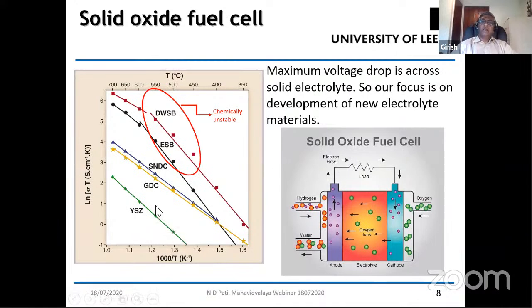Presently, the solid oxide fuel cell uses an oxide ion conductor, which is yttria stabilized zirconia, and also gadolinium oxide doped ceria as the solid electrolyte. There has been some research done into bismuth oxide based electrolyte, which has much higher conductivity than yttria stabilized zirconia or gadolinium oxide doped ceria. However, bismuth oxide based electrolytes are quite unstable at the low oxygen potentials that are present at the anode of a solid oxide fuel cell. So there is a problem there.